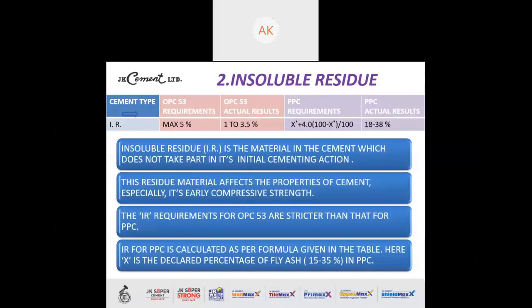Second and very important parameter for the chemical analysis is the insoluble residue. Now IR, OPC 53 maximum should be 5%. In India we get a range for IR. Now the PPC requirement is calculated by the formula 100 minus X bracket, declared percentage of fly ash added by the manufacturer. PPC actual result range is between 18 to 38% for insoluble residue.